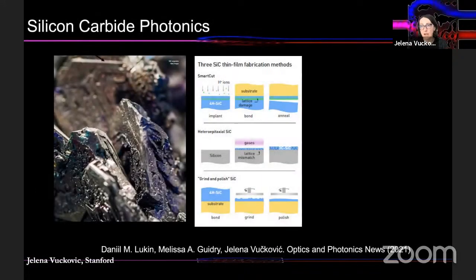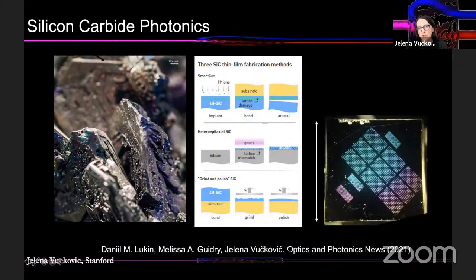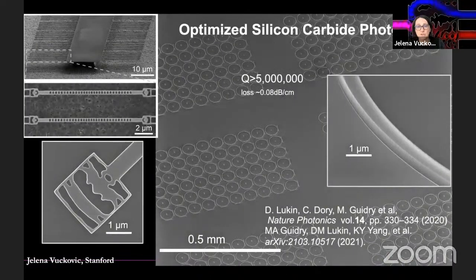But for silicon carbide, again, you have to start from bulk material and do something to make photonics. So how do we do that? People tried different things, but the only one that works well to make these pristine, high purity films of silicon carbide on insulator was the simplest thing you can think of. You take silicon carbide, you bond it on oxidized silicon, then grind, remove most of it, and then etch and polish. And that gives you a thin film of material on top of insulator. We can produce few by few millimeter films, but in principle it's scalable to larger scales. And we can also do it while preserving properties of all of the color centers. At the moment, in this silicon carbide material that we produce, we can build resonators with Q factors greater than 5 million.